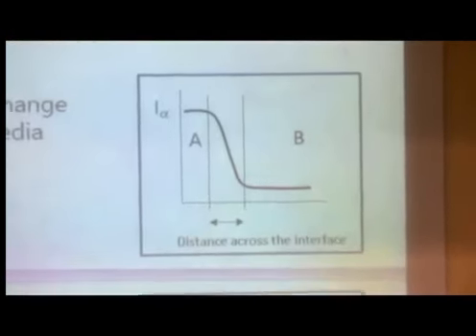It tells you that the intensity of any property across an interface does not change abruptly. As you can see here, property I, alpha, changes gradually when you go across the interface. And this can be more special. In fact, the intensity can even attain values which are larger or much smaller than both media, which is really exciting. So we create something which is really different from both constituents. The model, however, does not give any physical explanation. It's more like a visualization of what could happen on a nanoscale.